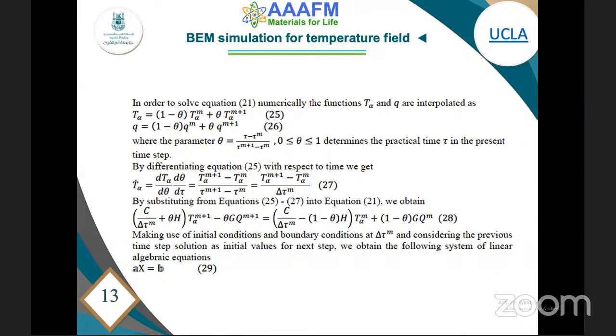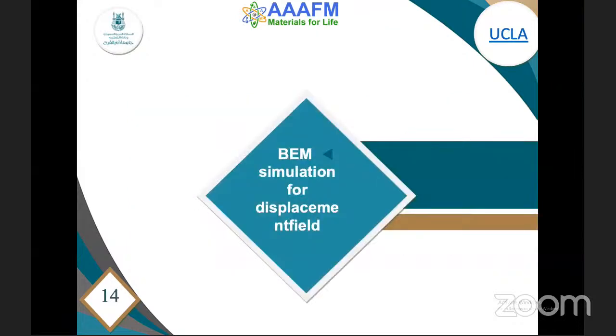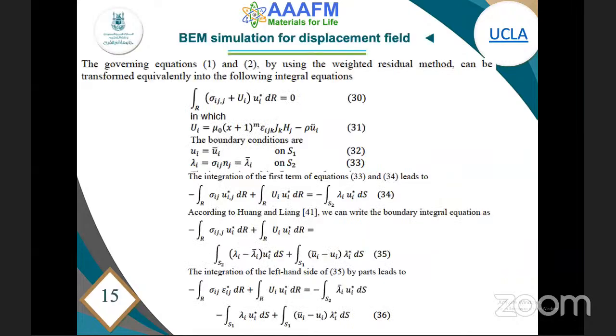Making use of initial conditions and boundary conditions at delta t and considering the previous time step solution as initial values for the next step, we obtain the following system of linear algebraic equations, 29. BEM simulation for displacement field. The governing equations 1 and 2, using the weighted residual method, can be transformed equivalently into the following integral equations 30, in which 31, the boundary conditions are 32, 33.